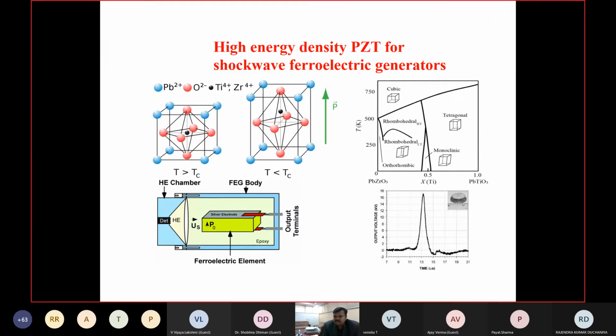So what we have chosen in our case, we have chosen the 95-5. I'm not able to show here, but 95-5 means 95% lead zirconate and 5% lead titanate, right? And because of that type of composition, the initial structure when we apply the electric field, that is ferroelectric. And when we apply the high pressure, how we apply the high pressure? We apply the high pressure by pulse, means shock wave generated by the explosive.